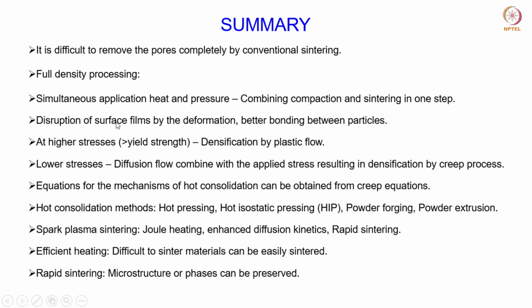So this will ensure that when the particles come in contact, a fresh surface is there for them to bond together. Okay, so the fresh surface will essentially give rise to a more effective mass transfer, and therefore the particles can bond together more effectively, giving rise to better densification. And if you look at the mechanism of this hot consolidation, where the heat and pressure are applied simultaneously, it basically resembles the creep phenomena, which is a high temperature deformation process that occurs at a constant stress.